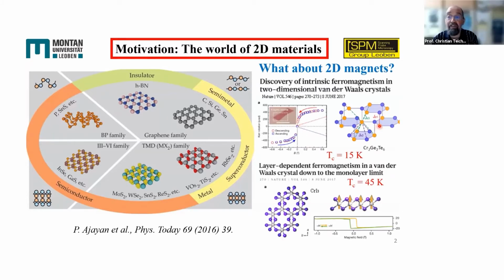And it took until 2017 that chromium germanium telluride and chromium iodide two-dimensional layers have been prepared, and they showed, in fact, ferromagnetic behavior, but only at very low temperatures. Within the last 5 years, there was a hype to search for room temperature two-dimensional ferromagnets. They have been found now, more or less, but only under UHV conditions, not air stable.